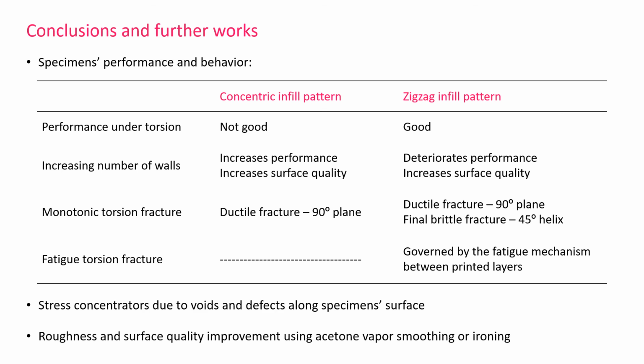From fatigue torsion tests, it was observed that the fatigue mechanism between layers governed the failure mechanism of specimens. From a fractography analysis point of view, different types of voids and defects were found along the specimen surface, generating stress concentrators that contributed to crack initiation. Further studies focusing on the reduction of surface roughness and improvement of surface quality, for instance, by using acetone vapor smoothing or ironing, are recommended.